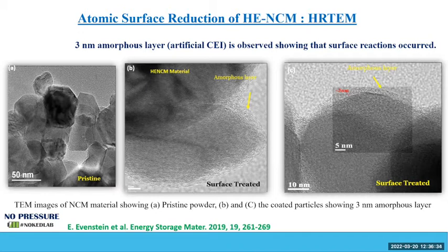One more thing I can tell you is that if I change parameters, and I will show you later with diethyl zinc, I'll keep this question, because we can follow the suppression of the transition metal signal in XPS. If I do that and with time it disappears, then it means it's a full coverage.